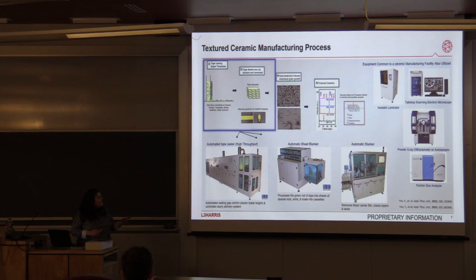We also utilize things that we typically have sitting in our ceramic processing factory. A really important part of all of this is maintaining a set of key processing indicators. The way we track that is powder X-ray diffraction, particle size analyzer, and then scanning electron microscope. We don't do this for every batch, but in ceramic manufacturing, when you see an issue, you have the tools to look at it, and also points when you need to look at these things to make sure that the product you're putting out at the final end stage is the same each time.